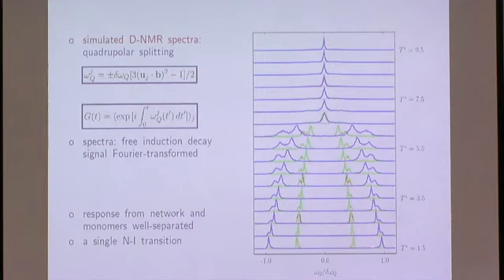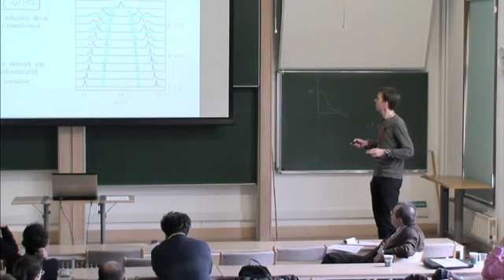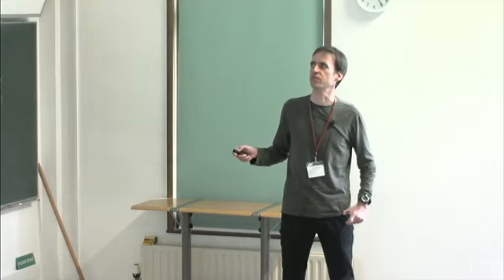Now, as we increase temperature, the splitting will go down. And what you will also see is that you will end up with a double peak structure on both sides. It turns out that the outermost peaks correspond to the contribution coming from the deuterated network, and the inner peaks here correspond to the swelling monomers. The swelling monomers are not bonded to the network, so they're a little bit more mobile, and this is why they're characterized by a slightly lower degree of ordering, and this is nicely visible here. But despite this two-component character of our system, it seems that we observe just a single nematic-isotropic transition, so there's no significant phase separation in our system.